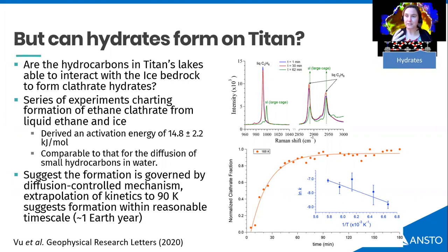We've done a number of experiments. These are done with Raman scattering at the Jet Propulsion Laboratory, and they found that when you put liquid ethane onto a bed of ice or grains of ice, you can actually start to form ethane clathrate. And we measured the activation energy of this and got the kinetics, and then extrapolated it down to 90 Kelvin. And what we found is that yes, you can form these gas hydrates, ethane hydrate, in a reasonable timescale. So it would take about a year at 90 Kelvin, whereas at 150 Kelvin it takes about 60 minutes to reach 60% completion. But in a Titan context, 1 Earth year is actually quite rapid.